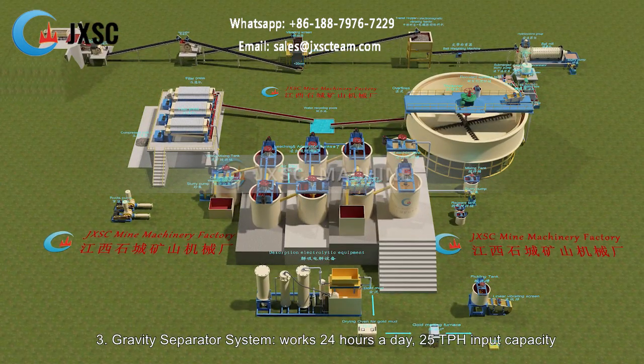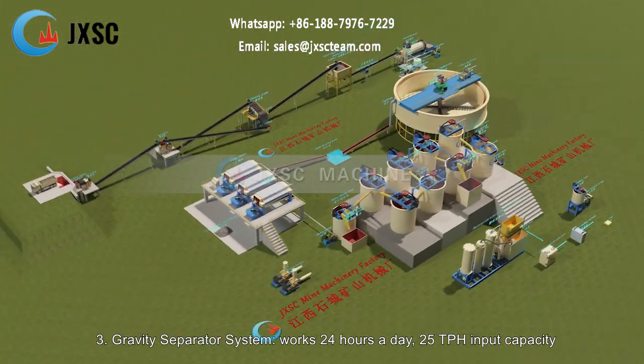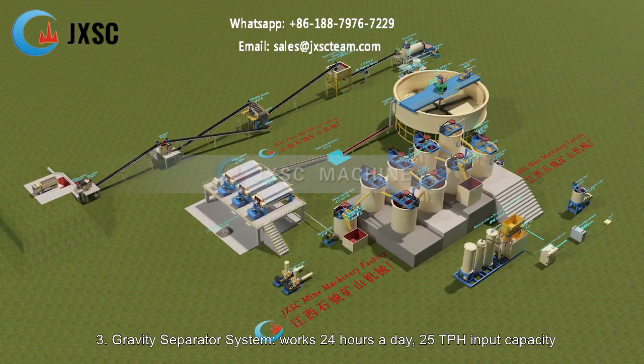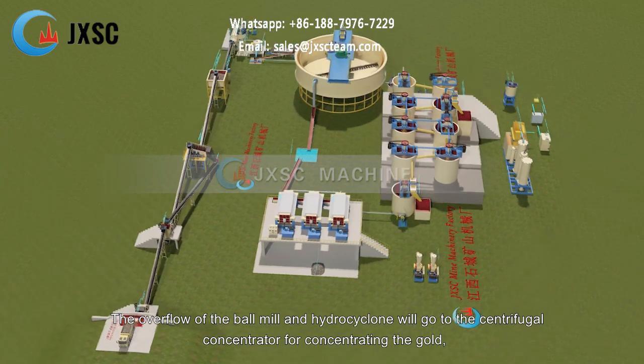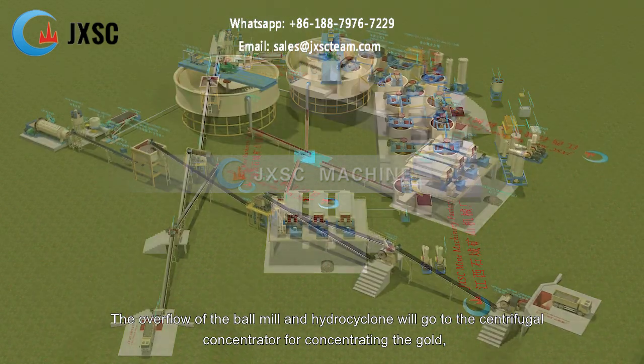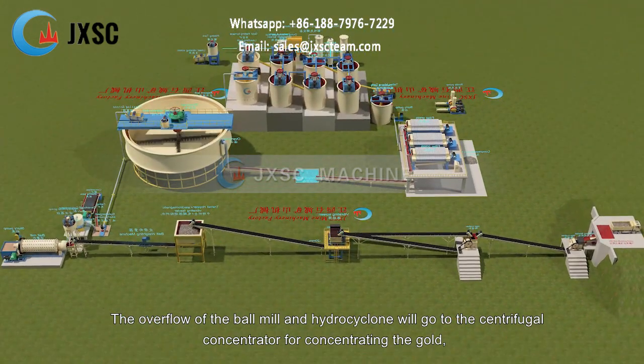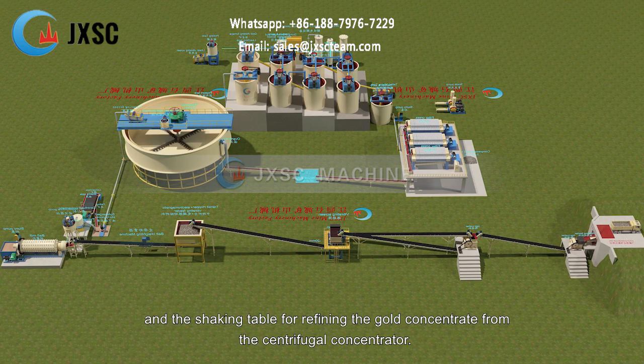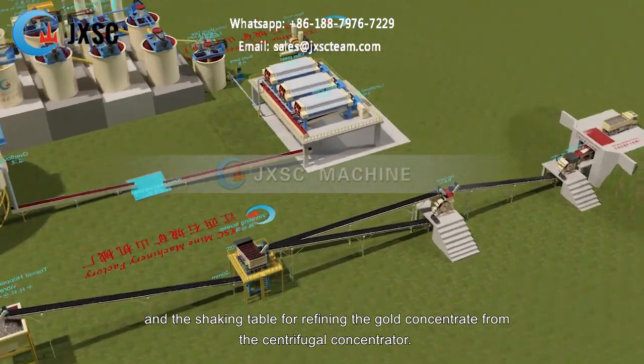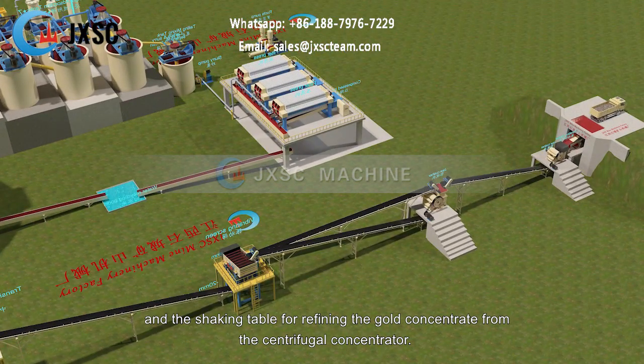3. Gravity separator system. Works 24 hours a day, 25 tons per hour input capacity. The overflow of the ball mill and hydrocyclone will go to the centrifugal concentrator for concentrating the gold, and the shaking table for refining the gold concentrate from the centrifugal concentrator.